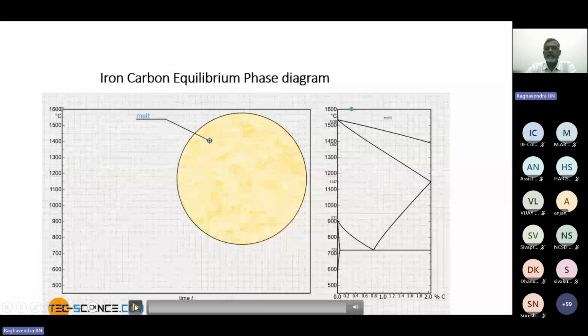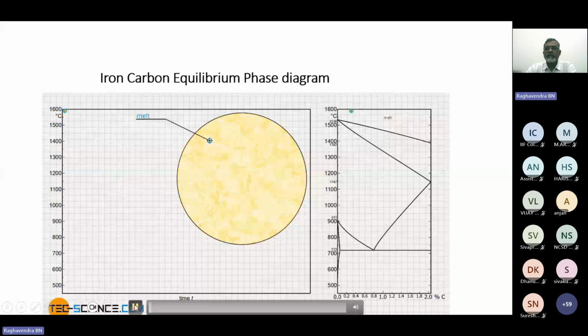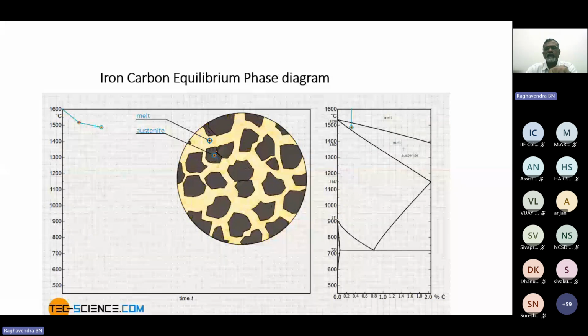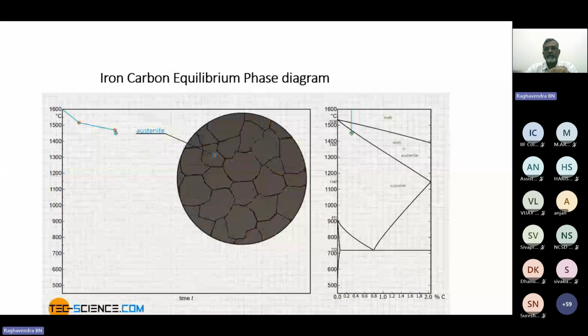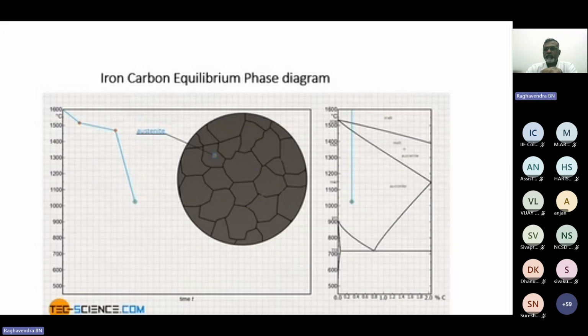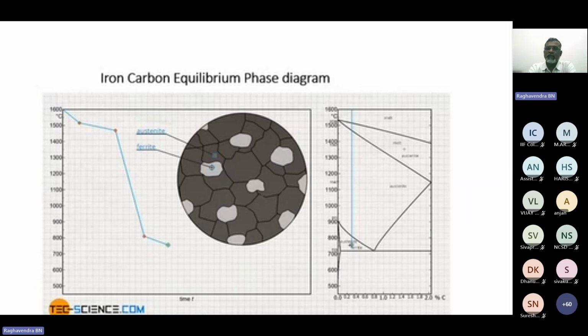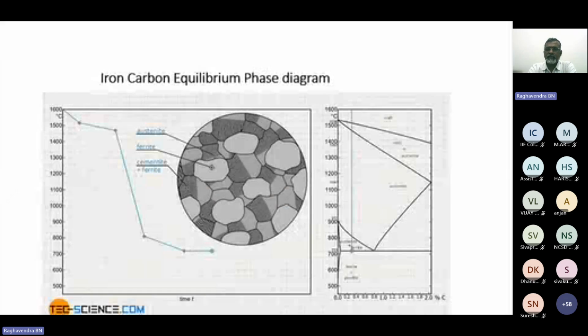this is completely liquid, right? Now when it touches this point, this is liquid plus austenite. This is how the crystal grains grow. Now it is completely solid. It is austenitic structure. Now we are slowly cooling it. Once this touches this temperature, the austenite plus ferrite transformation takes place, and this is the 723 line, that is the critical temperature line. Below this the transformation will be ferrite and pearlite.